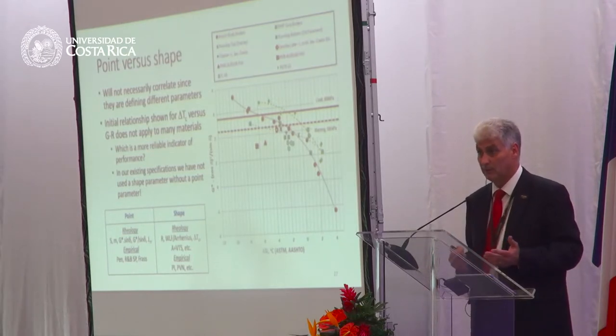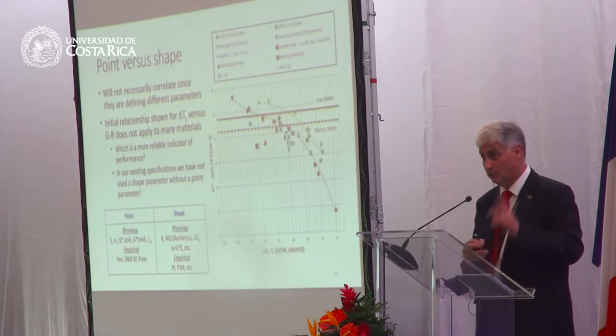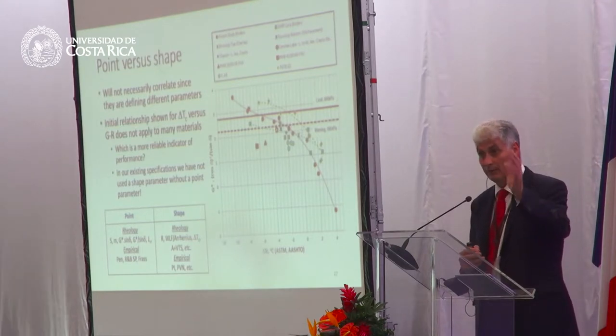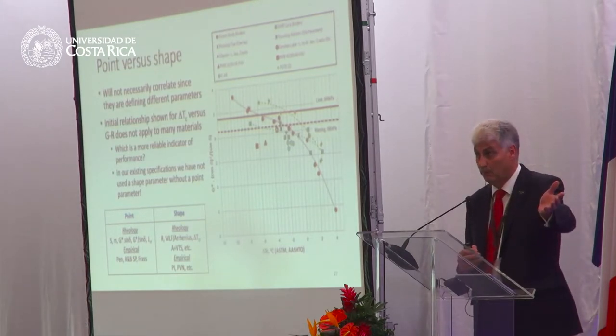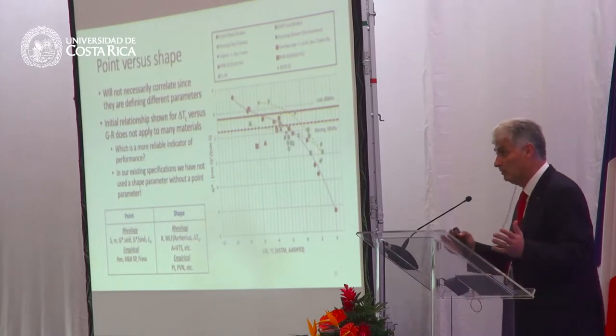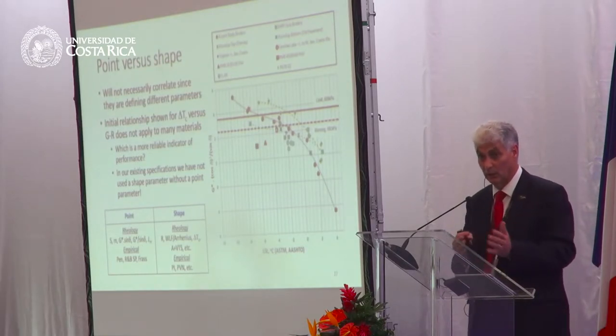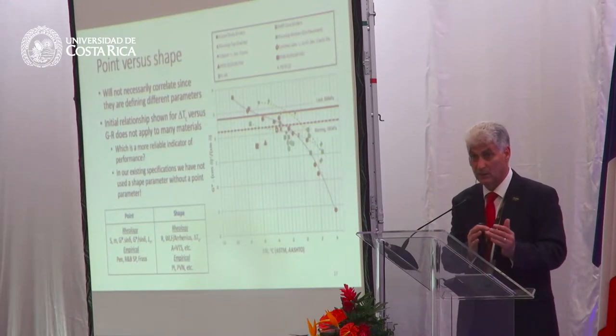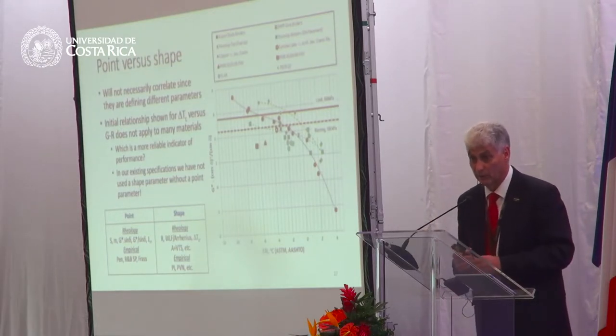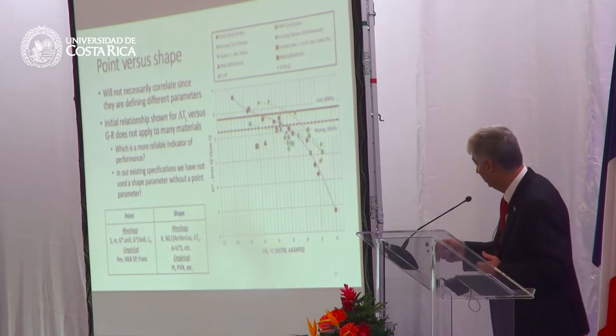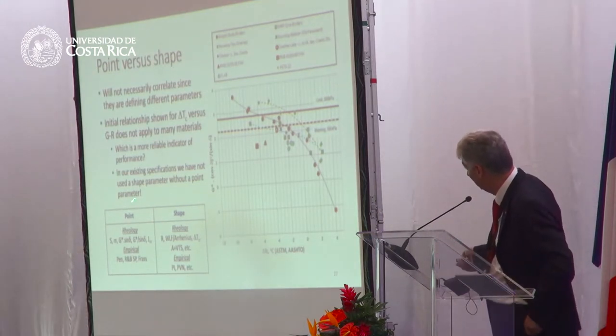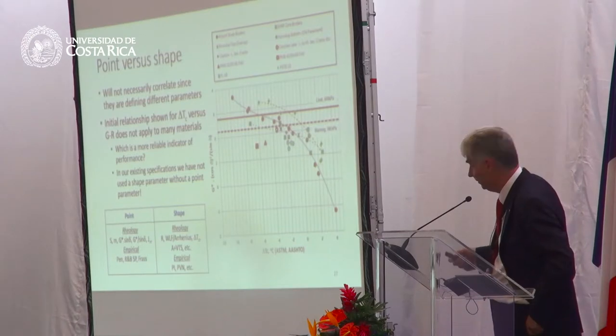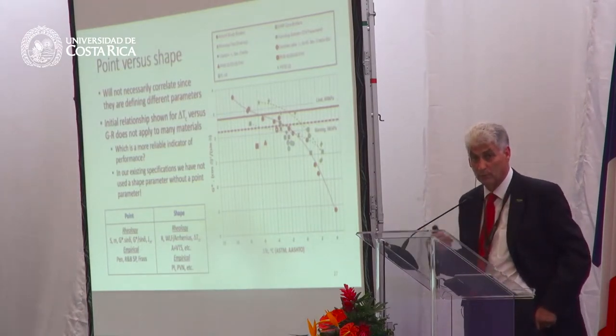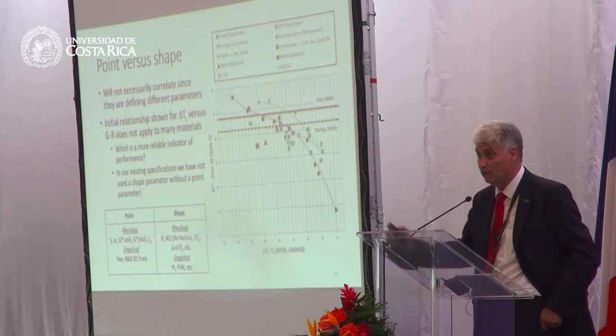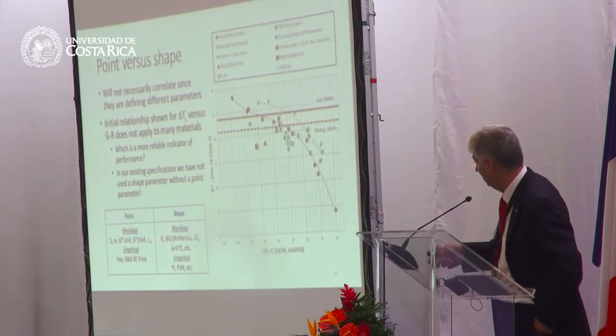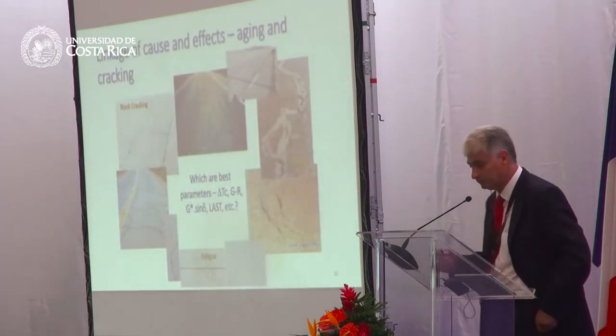We never developed historically a specification that just has one slope parameter. So we'd never have a specification that just says penetration index. So what this means is that we can't rely on delta Tc alone. We have to have delta Tc and some parameter to anchor it with to really understand our binder performance. And these are some examples of point parameters and slope parameters, and we've always used 2 or 3 of these parameters in our specification to fully capture the temperature and time dependency of the material.